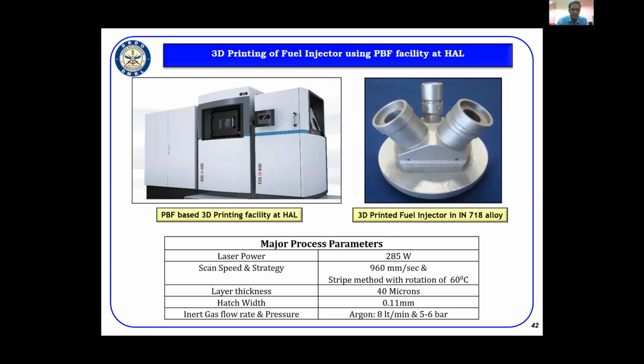And then again, we have taken this deposition using the optimized parameters mentioned here. The layer thickness we have adopted for each layer is 40 microns with a hatch width of 0.11. And the inert gas that has been used was argon at 8 liters per minute. And using this facility, this is the component we have 3D printed.